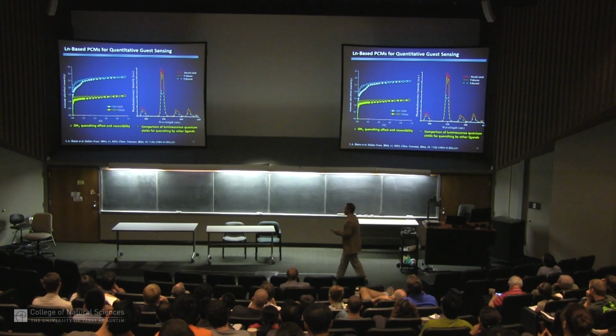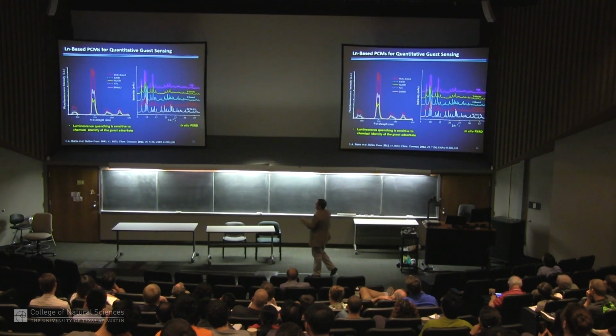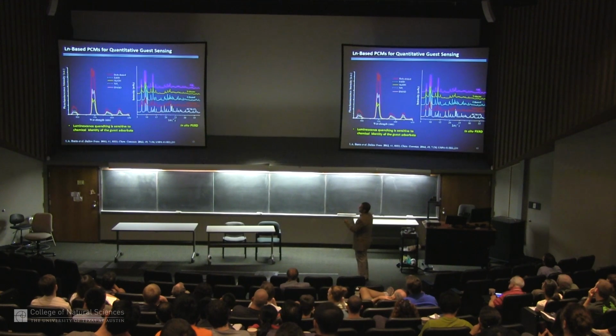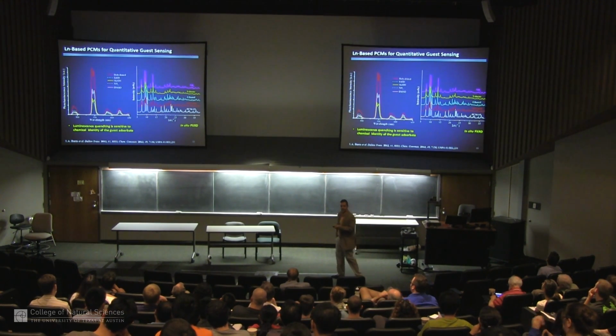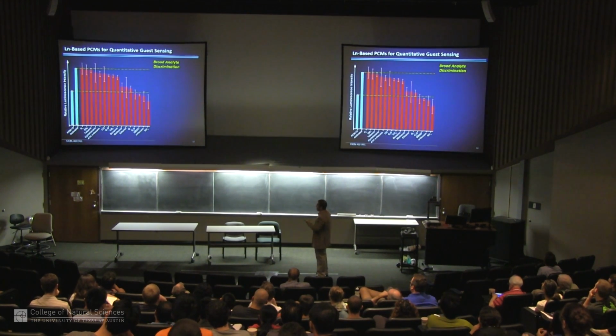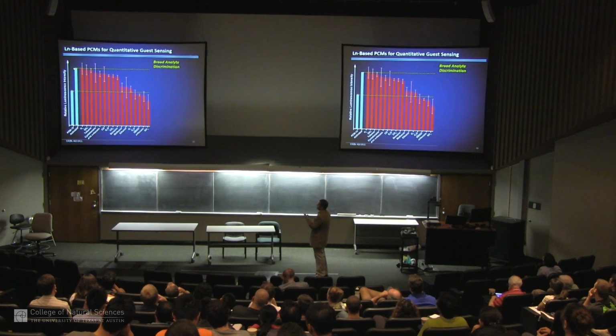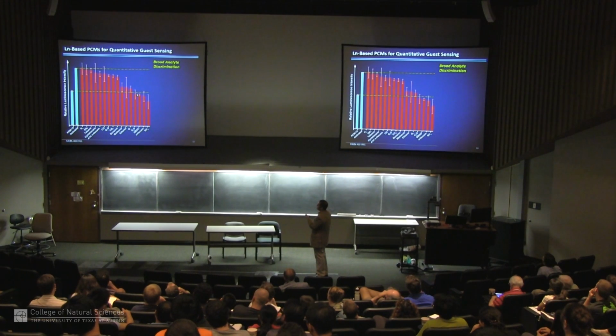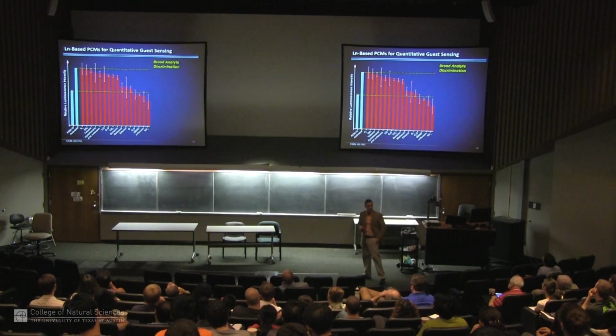So this is vapor sorption to show that the materials are always loaded. And we did this with a load more solvents and vapors and looked at the change in the luminescence, again just to show you that these materials completely retain their crystallinity. In fact, we went for a whole gamut of different small molecule gases and vapors, and based on the difference between the luminescence intensity or the quantum yield of the activated material versus the parent material, we can see there's a fairly gradual change based on the degree of quenching that each one of these guest molecules inside the pores will incur on the material.